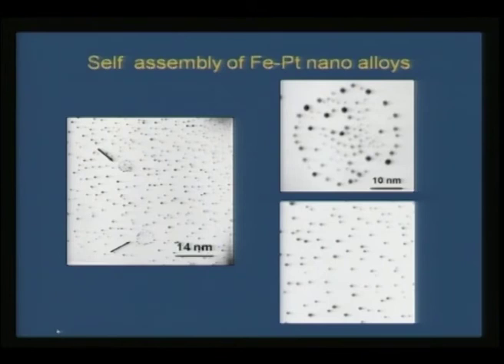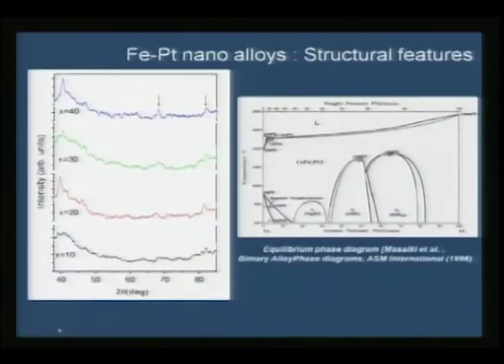Before that, you can see how the iron platinum nanoalloys form a self assembly. As you can see here, there are several regions where this sort of clustering of these nanoparticles is happening, which I have shown in this cartoon, and if you calculate the nanoparticles, these are typically from 1.5 to 3 nanometer size. So in such particle size we can isolate iron platinum nanoalloys, and if you actually look at the phase diagram, there are interesting things that we can understand.